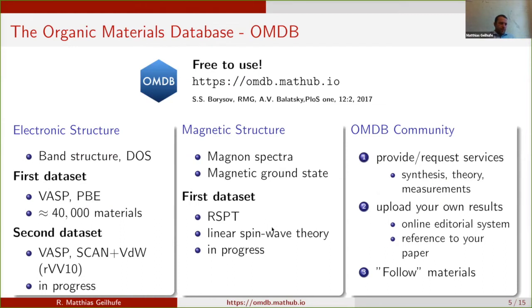So let me just briefly mention what we do. When I came to Nordita about 4 years ago, the first idea that we had was that we realized that in the realm of the Dirac materials, all the known materials at that time were inorganic. People discussed topological insulators like bismuth selenide or tin telluride, or the Weyl semi-metals, like tantalum arsenide and others. But we realized that there's pretty much no coverage on the organics. So we thought, why don't we just take the simplest approach, grab crystal structures from where we can find them and do straightforward PBE VASP calculations of maybe 1,000, 2,000 materials, and then we might get lucky and see 1 or 2 examples which we can discuss in more detail.